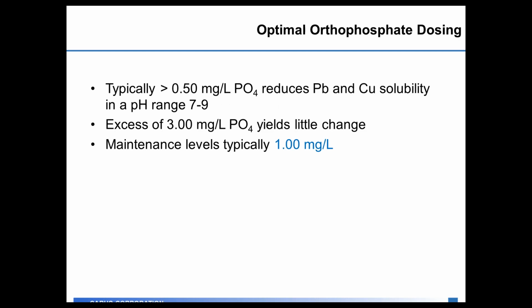A typical optimal orthophosphate dose would start at least 1/2 milligram per liter as orthophosphate to reduce lead and copper solubility in a pH range of 7 to 9. The current EPA guidance manual talks about feeding up to 3 milligrams per liter. Why that is because once you get above 3 milligrams per liter as orthophosphate in the distribution system, it yields little change in the reduction in lead and copper that you would see in the distribution system. Typically, most water quality plants will maintain a level anywhere from 1/2 part to 1 milligram per liter if they're just feeding an orthophosphate product to the distribution system.